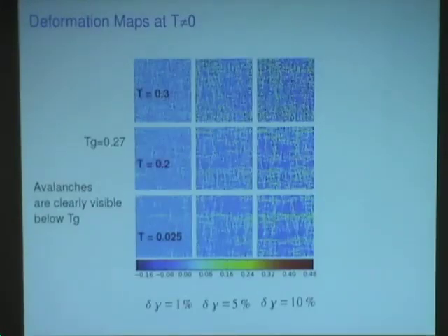So at least in everything we've done on these potentials, in the steady shearing limit, they don't seem to want to persistently localize. They will localize just enough to allow enough displacement to accumulate, and then they move somewhere else.